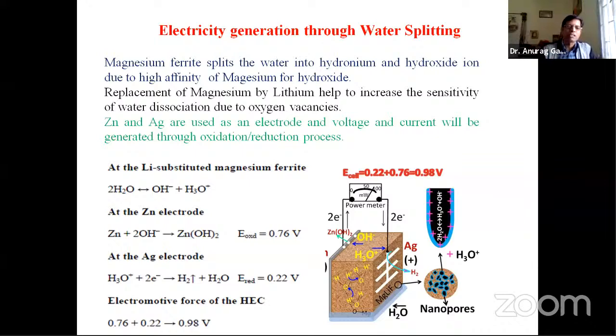Its structure is spinel based. But what we are doing is changing its morphology and topography, changing the grain size, increasing the porosity, and improving the surface area. You can do these kinds of things with materials, and you will find that for a lot of materials the properties change drastically once you change their morphology. The same thing we are doing here, making this material porous, because porosity is very important. If water is not absorbed in the material, the water dissociation will not take place, and you will not get any current.